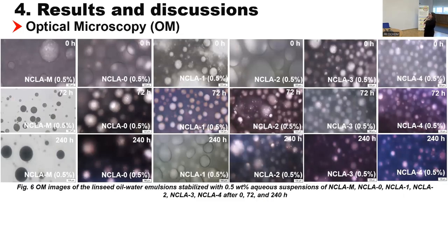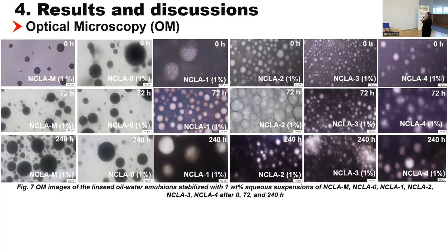The optical microscopy images are in agreement with the stability studies that I have presented before. We can see that the smallest droplets and the narrower distribution of the size of the droplets was obtained in the last two cases, last two columns, NCLA3 and NCLA4. The same observation remains valid at a concentration of cellulose in the emulsions of 1%.